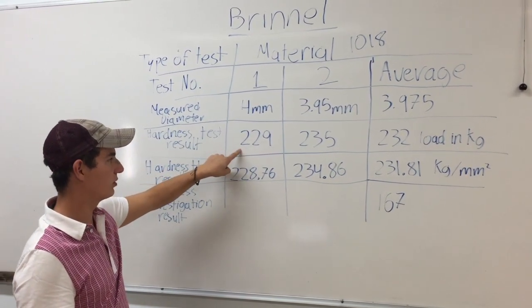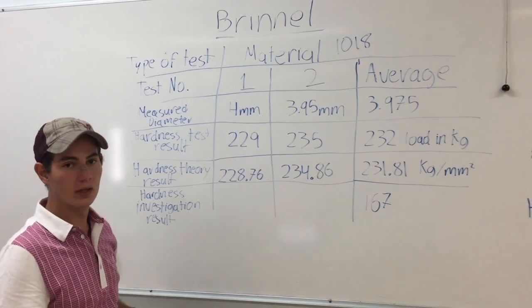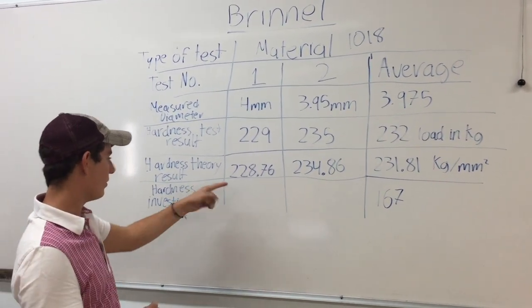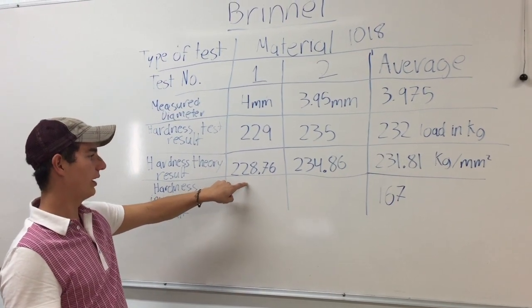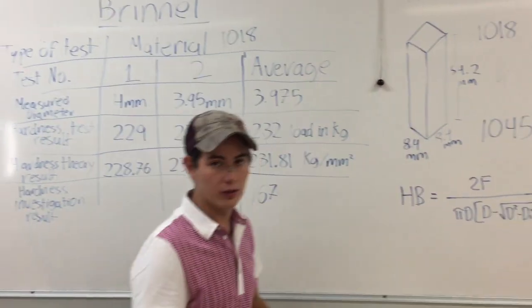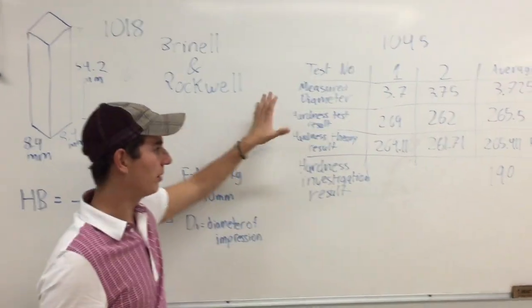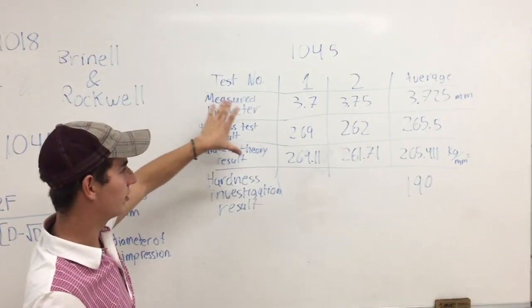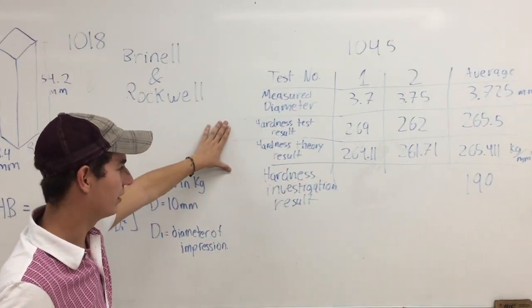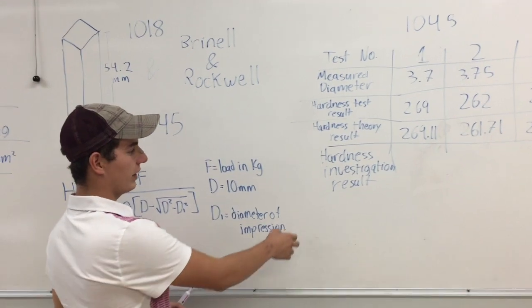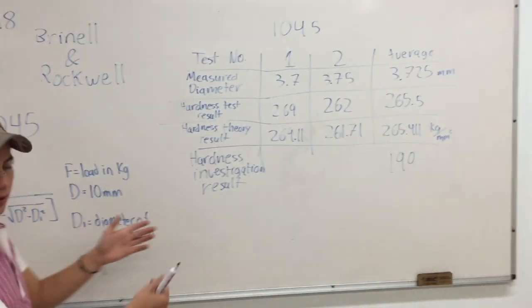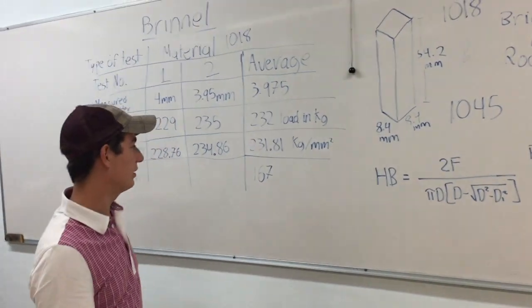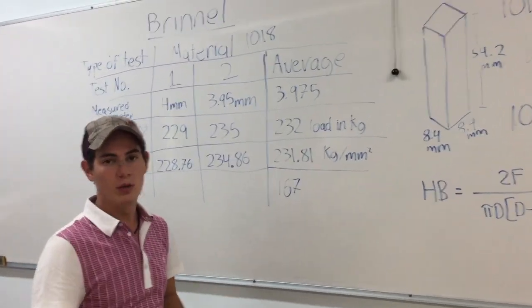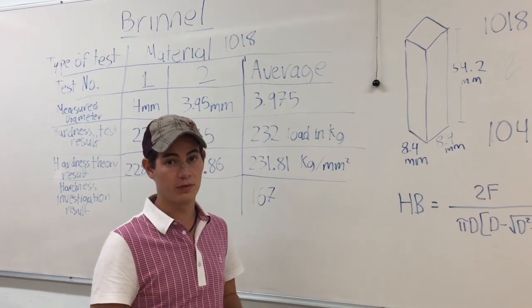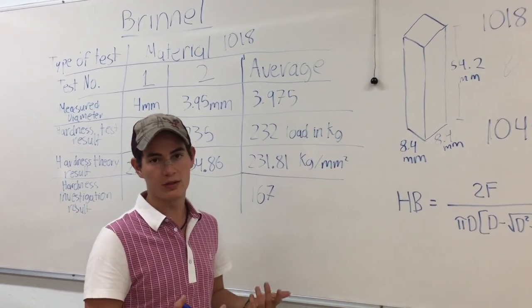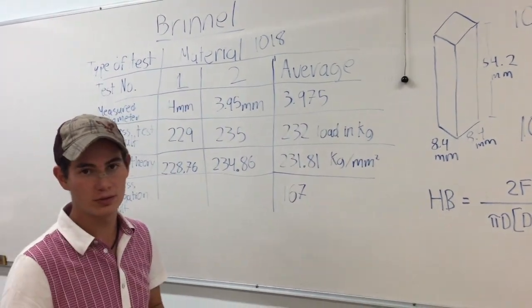The hardness test result was 229 when we applied the formula, and the theoretical hardness result was 228.76. For the piece 1045, we applied the same concept. We measured the diameter, the hardness test result, and the theory, and then at the end we looked at the hardness investigation result for both materials, and they were really different. We don't know why we got such different results, perhaps because of the temperature, or perhaps we did something wrong, but this is how we obtained all the results.